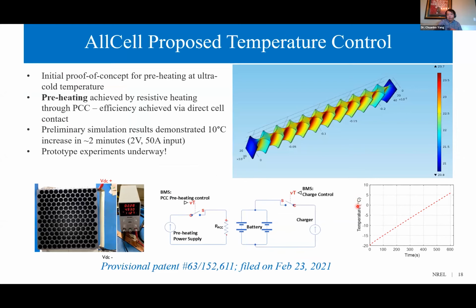Considering temperature management is required for fast charging, a technology expanding the current use of phase change composite technology is proposed by Allcell. This is done by using the phase change material incorporated between individual cells as a resistive heater. This proposed technology will enable direct rapid heating of individual cells due to the pre-existing phase change composite lithium cell integration and thermal transfer concept already established, without impact on energy density and cost from an increase in battery preheating components. The phase change composite will need to be designed to enable rapid preheating while still maintaining substantial thermal conductivity and latent heat characteristics for passive thermal management performance.